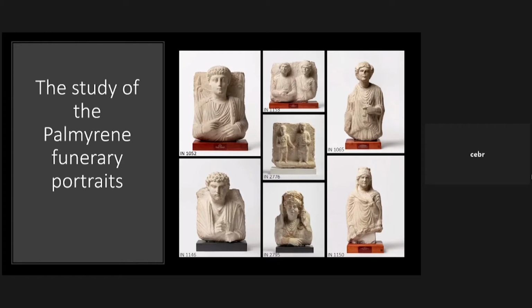In 2018, a survey of the collection of Palmyrene funerary portraits was carried out using VIL and visual examination. Based on this survey, 6 portraits were selected for closer analysis due to their particularly promising visible traces of polychromy. The chosen artifacts include different motifs and types and represent different chronological periods from about 150 to 250 CE. The portraits consist of 4 loculus reliefs and 2 sarcophagus figures.